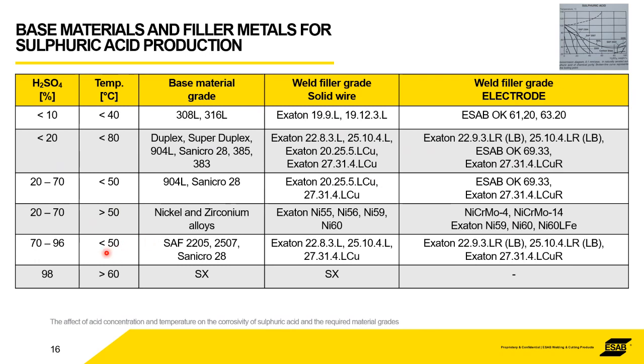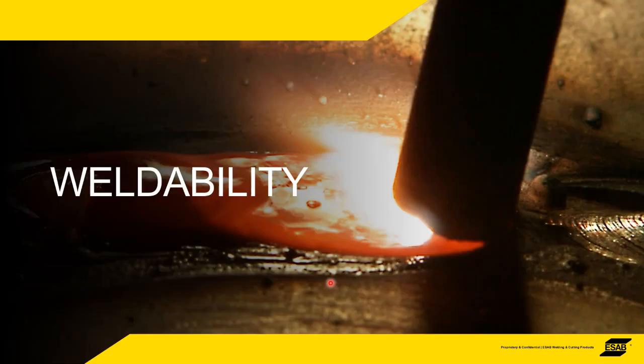Once you get above 70%, then things get a little bit more scary, and surprisingly we've got duplex and super duplex in here. So we have duplex and super duplex covered electrodes as well. Above 98% strength and 60 degrees, there is only one option and there's no electrode. So this is SX, a Sandvik proprietary product that's available from ESAB.